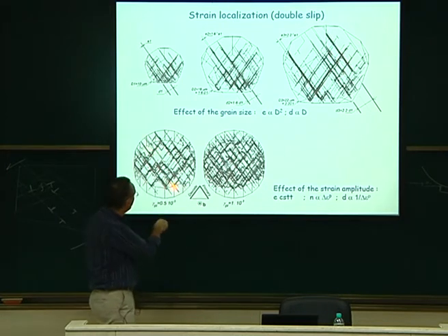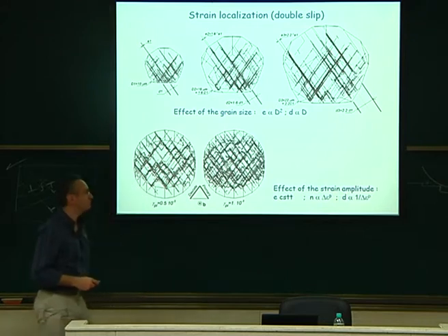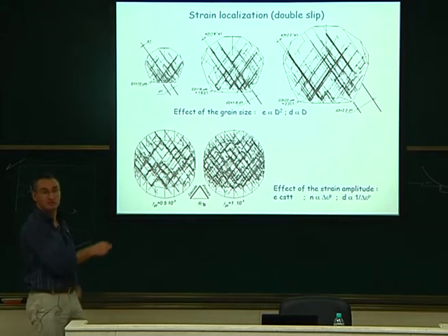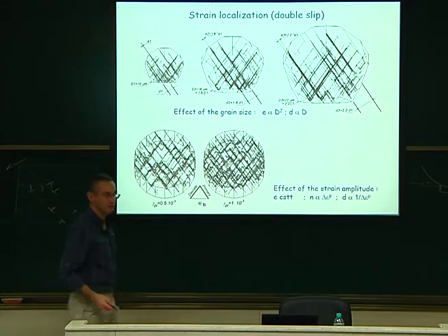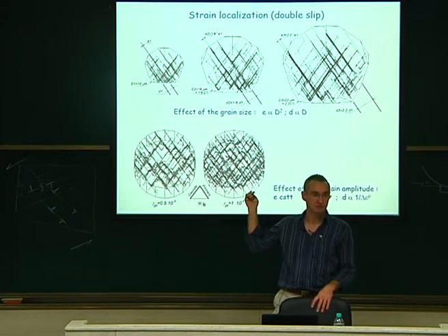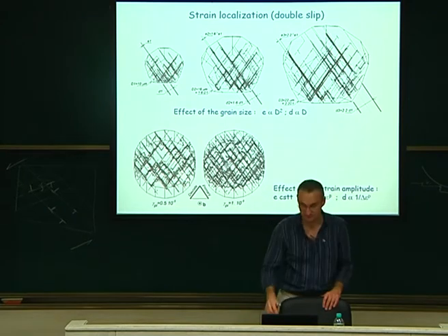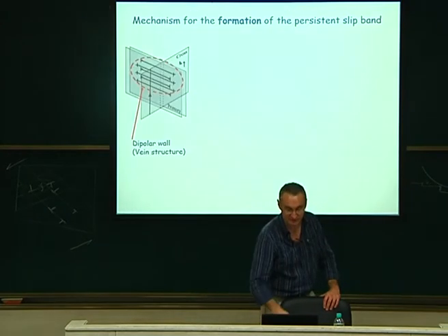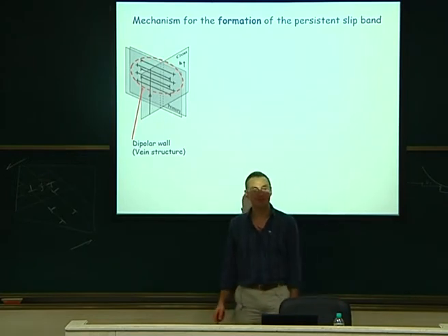So it means also that the number of bands is linear with the plastic strain amplitude. Or you can also say that the distance between the bands is the inverse of the plastic strain amplitude. So this is just, let's say, a parametric study we can do very quickly, and you can get this. A simulation typically takes a week. It's less than a week to get this. Okay. To give ideas.